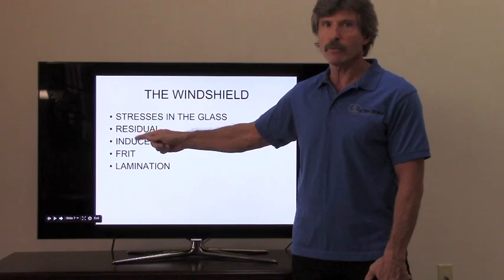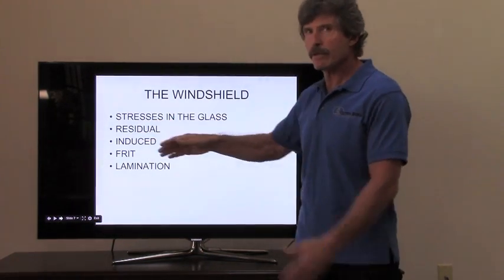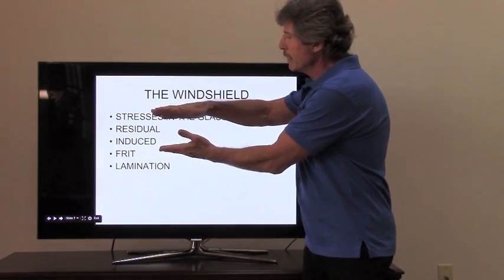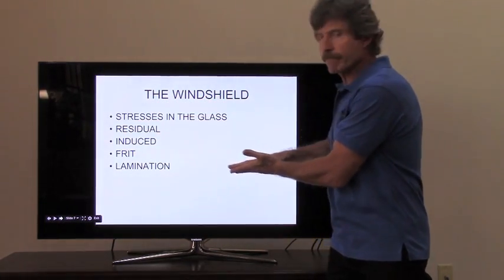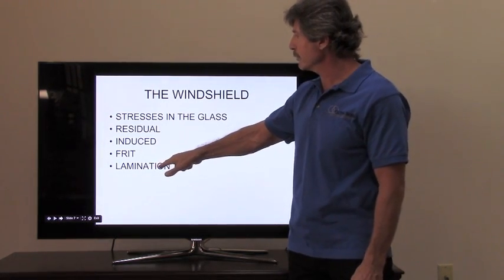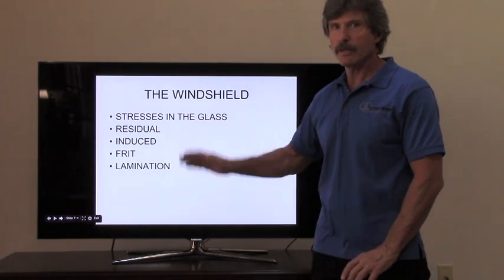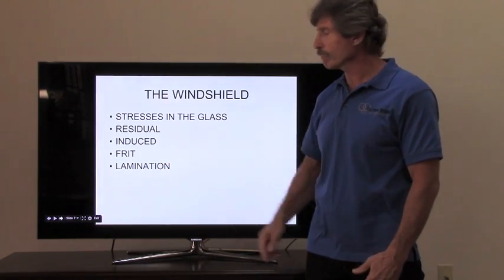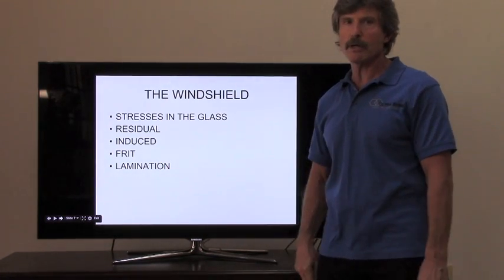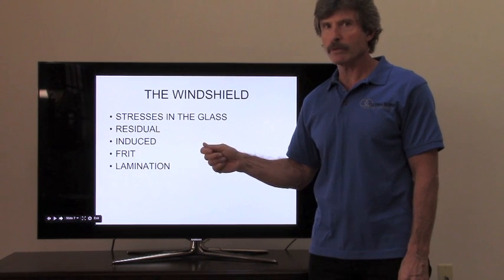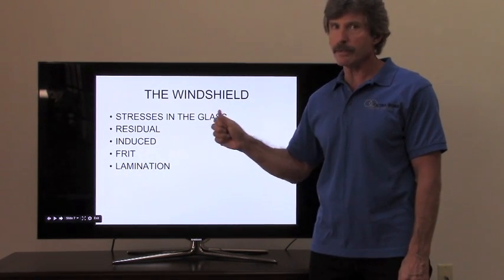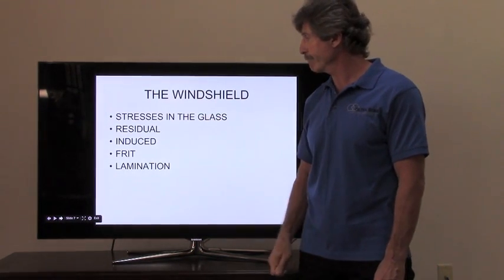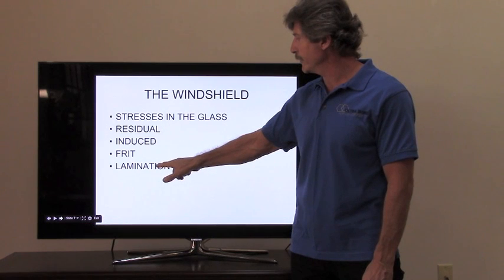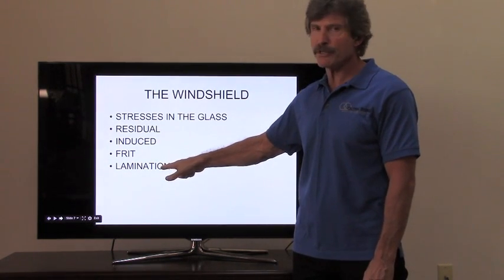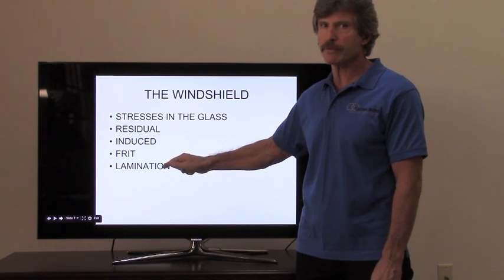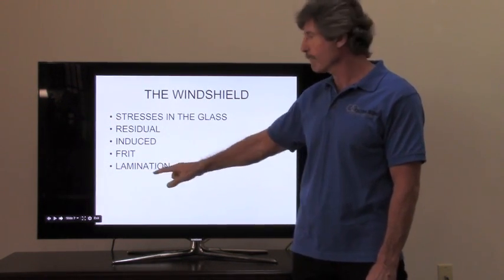When you get an edge crack, when a chip occurs in the weak spot and it cracks out, that installation stress pulls it apart, and then the lamination PVB bond pulls it back together. And it stops when this stress becomes greater than that stress. That usually stops the crack. It's usually around 8-10 inches. That's also why you can pry the crack open to get your resin in on an edge crack or a floater crack, and it doesn't spread on you unless you push too hard. But that's your friend. The lamination stress is helping you out on a repair by 3,000 psi. So your repairs already have a 3,000 psi help or bond from the lamination holding things together.